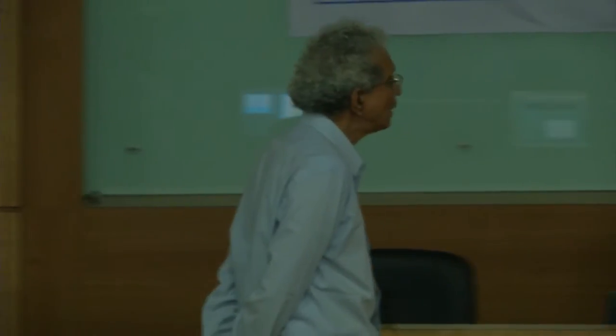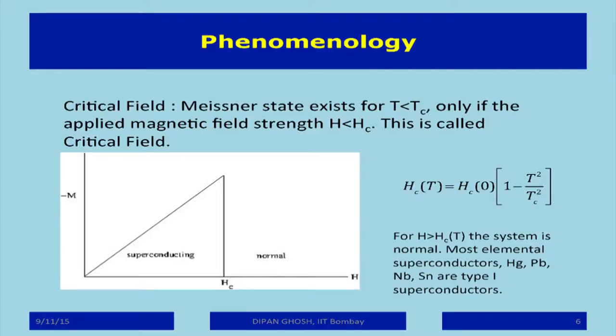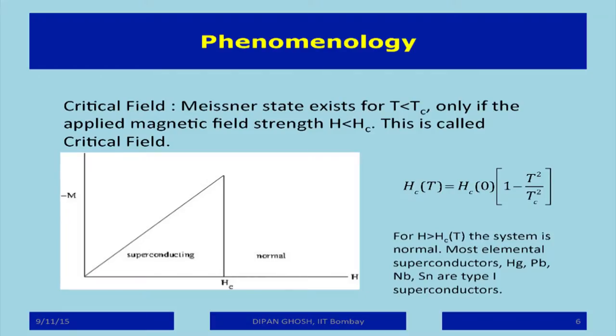Most of the elemental superconductors, typical examples being mercury, lead, tin, niobium, follow this principle. That is, you apply a magnetic field at a given temperature when they are superconducting, and as you increase the strength of the magnetic field, you will find a limiting or critical value of the field, the critical field, at which the superconductivity will vanish. Such materials are known as type 1 superconductors. Type 1 superconductors are those where the magnetic field destroys superconductivity in this fashion.